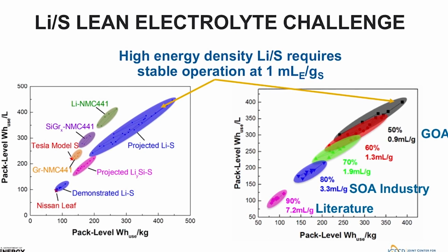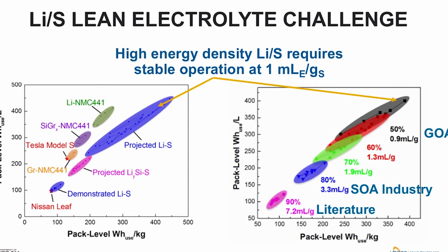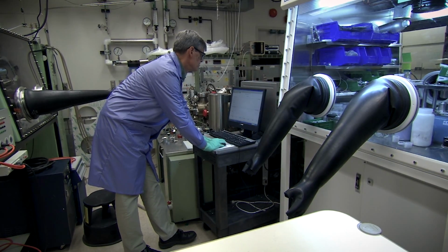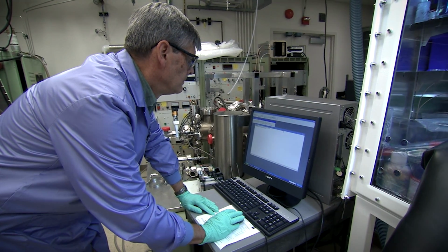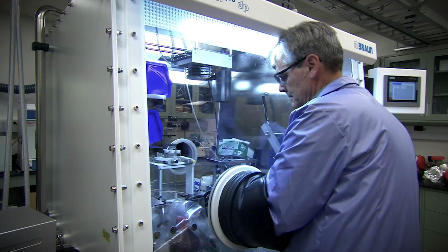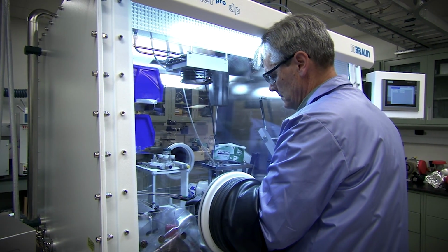The way we approach this challenge is to think about redesigning these electrolytes essentially from the ground up. And what we're specifically after is creating an electrolyte that's capable of supporting the types of rates, the power that we need, and the stored energy content that we're trying to achieve in practical lithium-sulfur batteries. And the key to that is reducing the amount of electrolyte that exists in these batteries. So in this perspective, we're motivating the use of sparingly solvating electrolytes with protected lithium metal as a means to achieve high energy density and long cycle life.